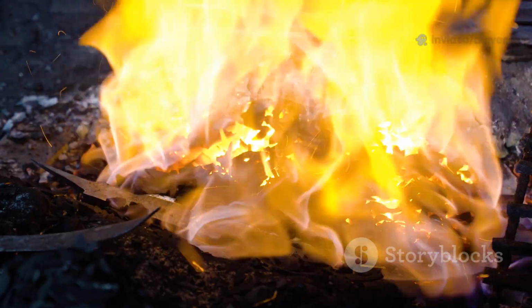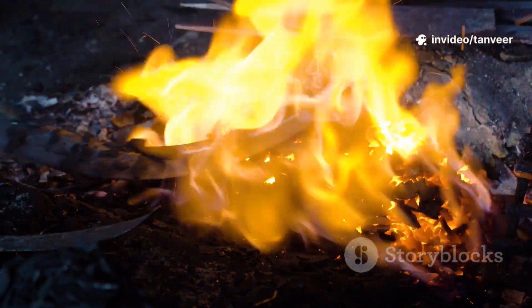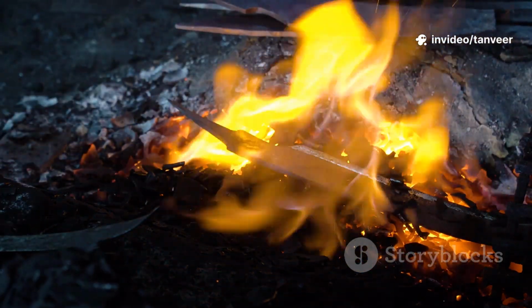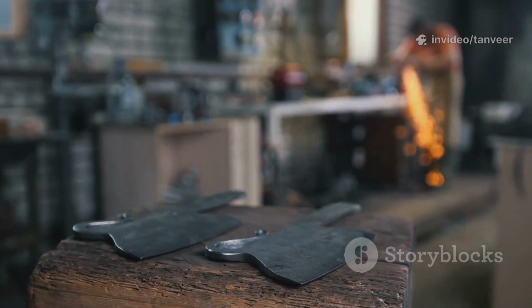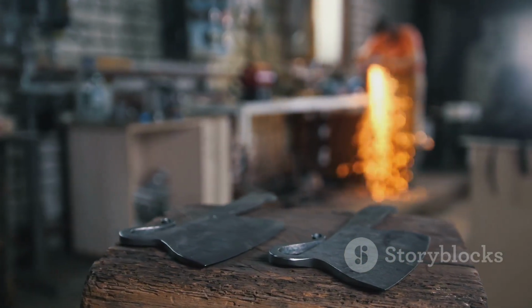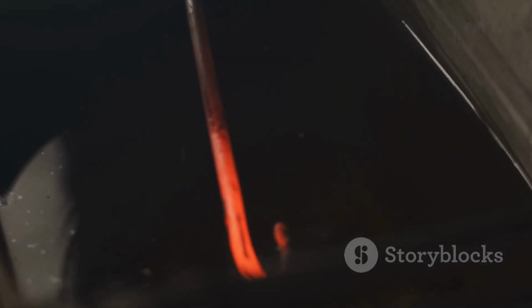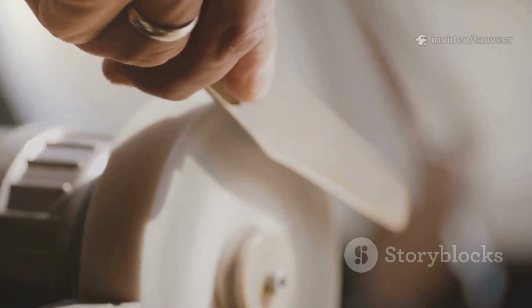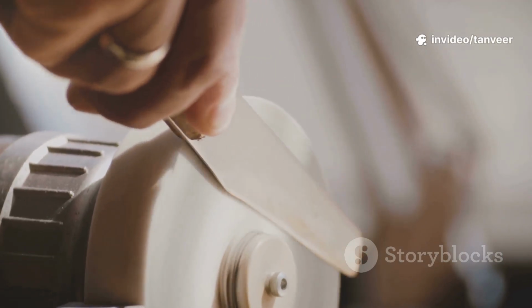The blade is now hard but brittle, so we temper it at 400° twice, to add toughness. This balances hardness and durability, ensuring the blade holds an edge without chipping. After tempering, I check for warping and confirm the core is centered. Only a slight warp appeared, easily fixed during grinding.